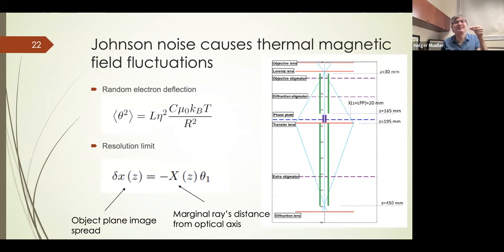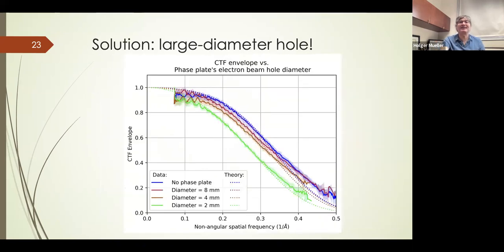Remember that little 2 millimeter hole that the electron beam has to pass? Well, the electrons inside the metal walls of this hole are at room temperature. They are moving around thermally, and that causes random magnetic fields that cause random electron deflection and therefore a resolution limit of the image. Jeremy developed a method of computing these things that I won't go into. And it turns out that with these Johnson noise effects, we could perfectly model the effects that are going on in our microscope, and we also take into account Cc, chromatic aberration.